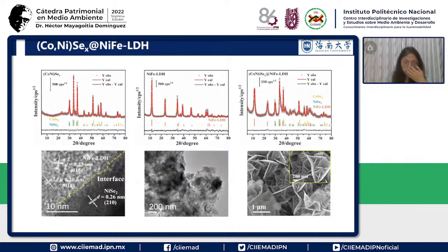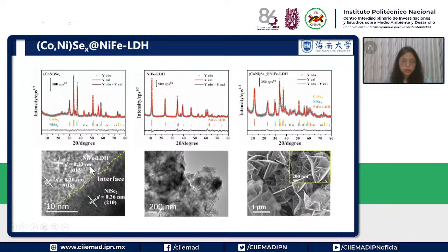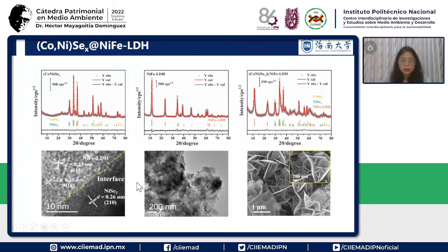And for these two materials, we also made this beautiful work, which comes from Luis. In this composite we find the cobalt selenide, the nickel selenide and the nickel iron LDH. In the HRTEM we found there are two distinct regions. On the left belongs to the nickel iron LDH, here is the interface, and on the right we find the nickel selenide. Maybe the cobalt selenide is not here.